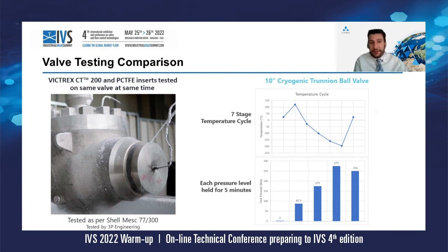Using a 10 inch top entry ball valve, class 1500s, from minus 196 to plus 120. We couldn't go higher because there was a PCTFE insert inside, and PCTFE cannot withstand, as we said, temperatures higher than 120 maximum. And we made the TAT test as per the Shell Mesc 77/300, which allows for very low leakage rates. And we have measured the leakage and the torque.